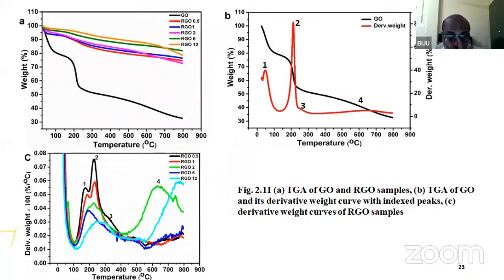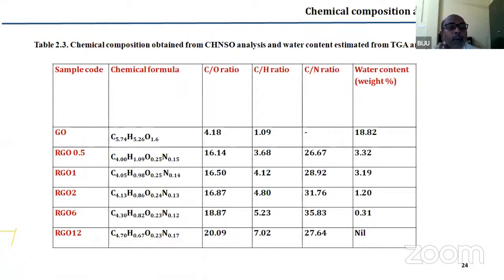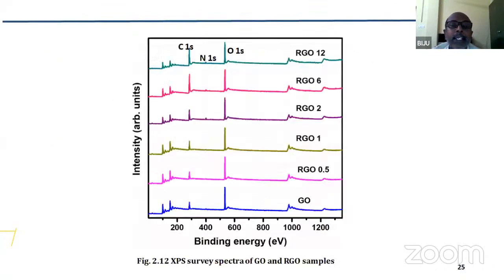Now, we also did the TGA studies and combined them with CHNSO analysis to obtain the chemical composition of our RGO samples, which are listed here. So our GO sample was something like C5.74H5.26O1.6, with a water content of 18.82 weight percentage. And as we reduced, the C by O ratio increased, the C by H ratio increased. There was some nitrogen incorporated since hydrazine hydrate contains nitrogen, and the C by N ratio also increased, and again the water content decreased.